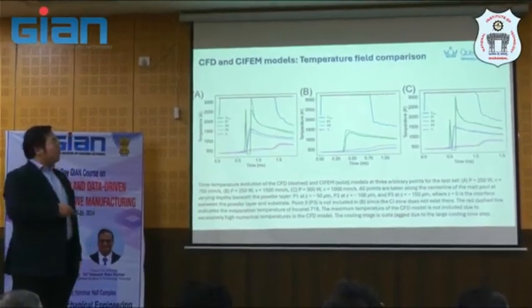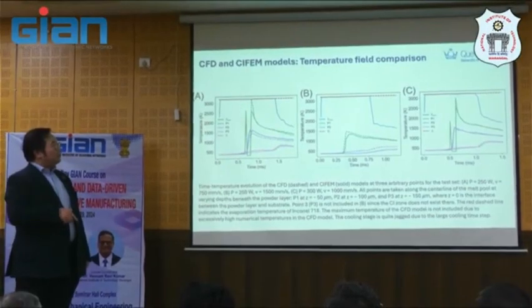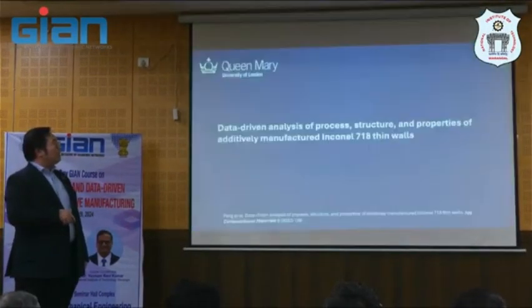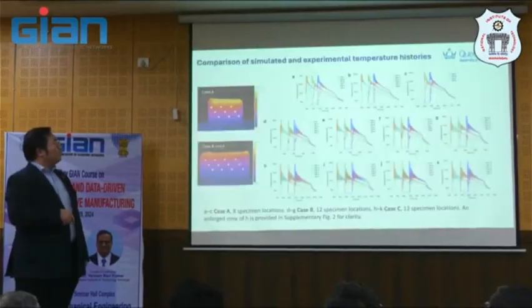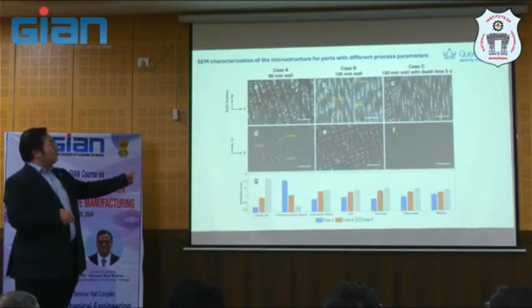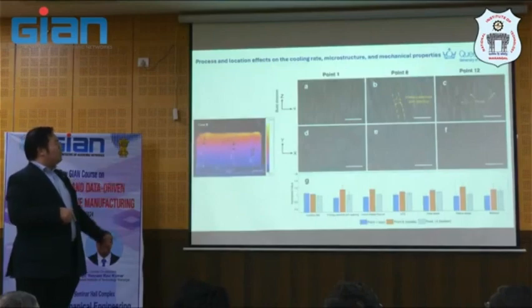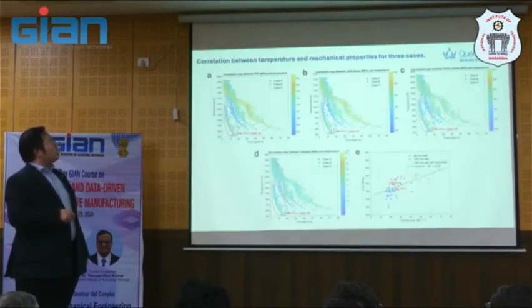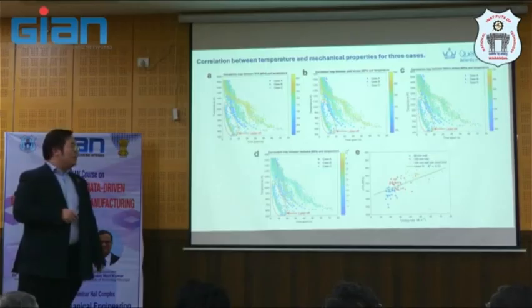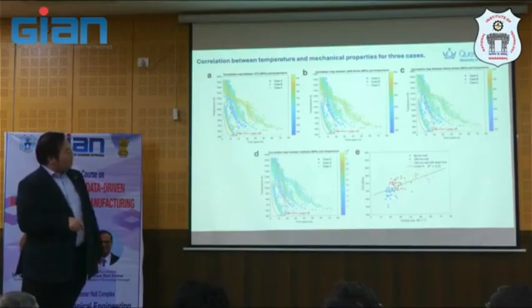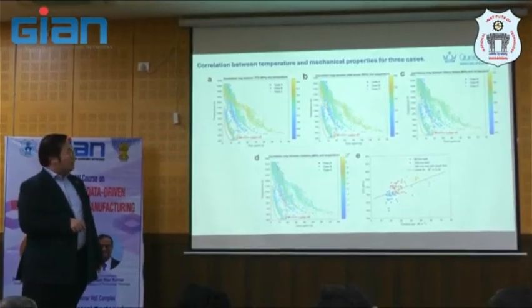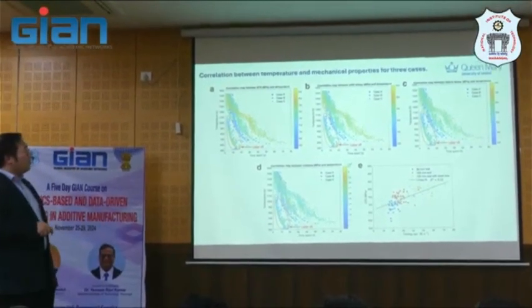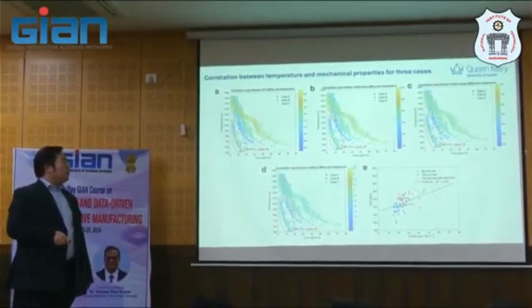during the 3D printing. As you see here, this one can capture, but imagine if you can combine this with the way you do this one, which is in another additive manufacturing process, and then we can actually get the relationship between temperature and mechanical property. And this is a perfect scenario where we want to predict as a function of cooling rate, and then you will see the property has a correlation with the UTS, and this is the ultimate aim that we want to get.